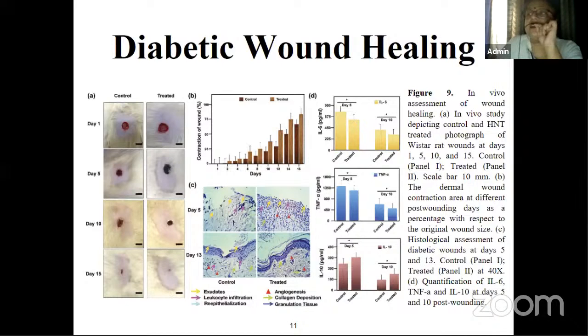In contrast, the control tissue displayed vascular insufficiency and limited cell recruitment to the territories, which delayed wound healing. So we believe that an orchestrated interaction of cells with HNTs at the wound bed synergistically improves healing by day 12. Thus, the inhibition of IL-6 and TNF alpha and a concomitant upregulation of IL-10 revealed the anti-inflammatory potential of HNTs, where low IL-10 prolonged the inflammatory phase in the control group.